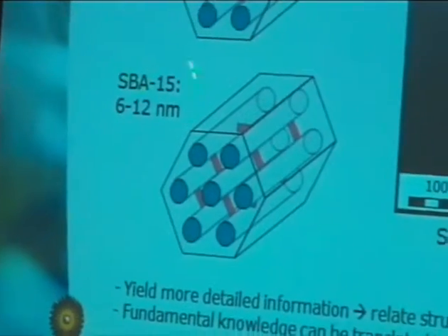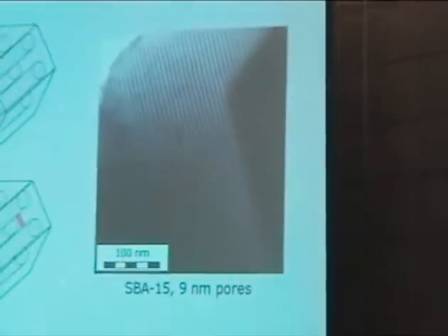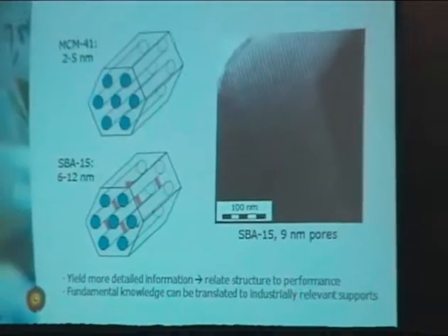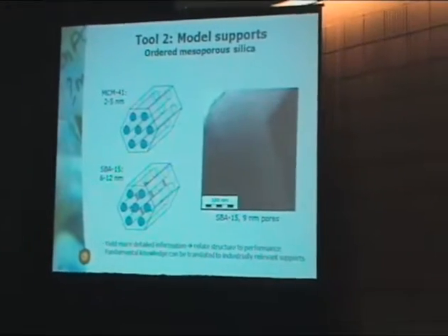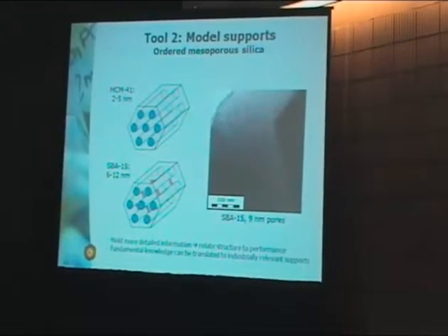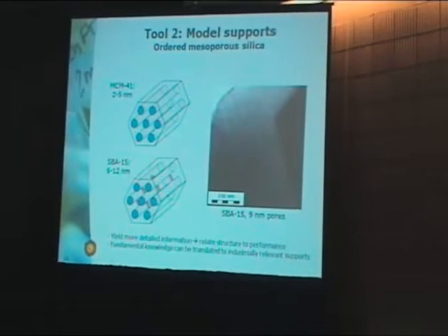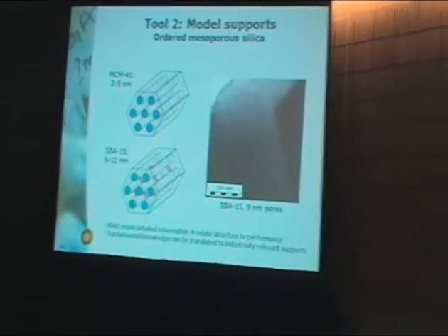We use model supports, for example, ordered mesoporous silica like MCM41 and SBA15, with the mesopores well ordered with respect to each other. In this case, SBA15 with 9 nanometer pores is something that assists us to derive fundamental relationships, you might say synthesis, structure, performance relationships.